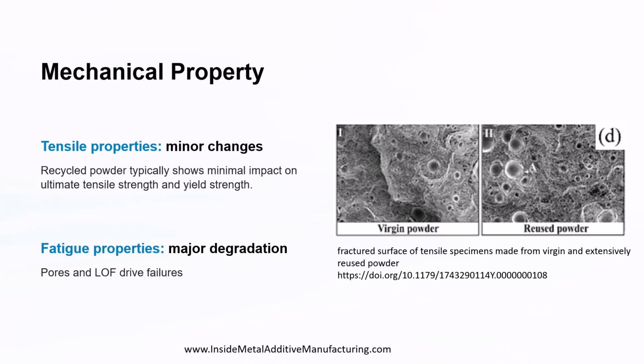When it comes to tensile properties, the impact of powder recycling is surprisingly modest during early reuse cycles. Tensile strength and elongation remain reasonably stable, with only minor reductions that can usually be traced to slightly increased porosity, chemistry drift, or subtle microstructural changes. Fatigue properties, however, tell a very different story. This is where powder reuse becomes a critical concern.